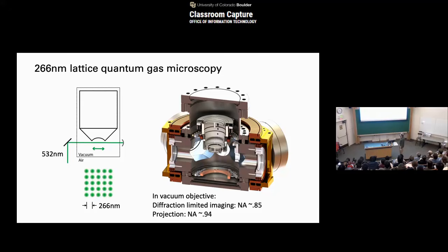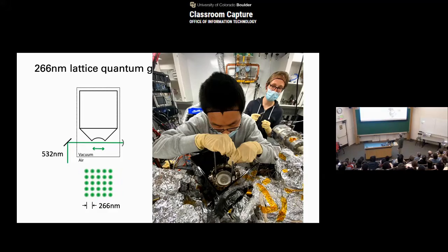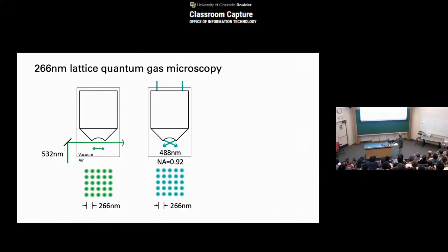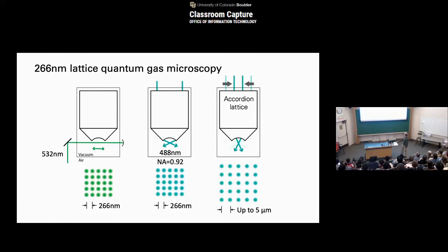We have a very high numerical aperture objective inside the vacuum chamber. We're not only using that to image, to scatter photons, but here you can see a picture of how we put it in. We also use it to create a lattice potential that we can zoom in and out. So first we have a green standing wave like this, and then we superimpose a lattice made out of blue light that comes through the objective and exactly matches this. And then we can change the laser beams and increase that lattice spacing. At least conceptually, it's very, very nice and simple.